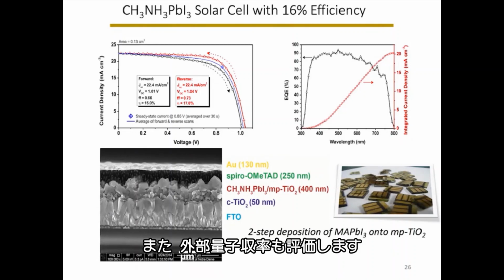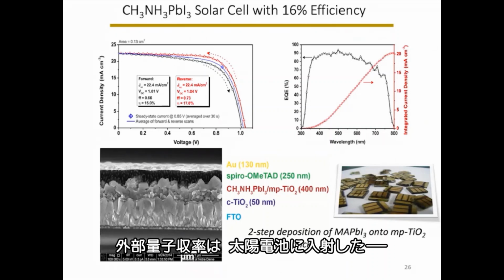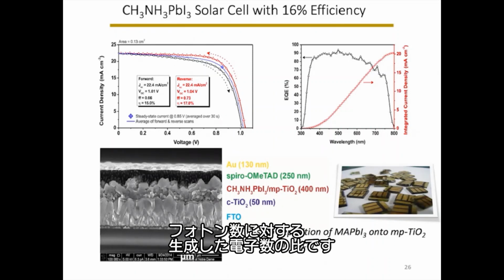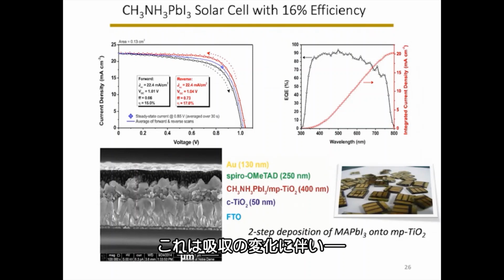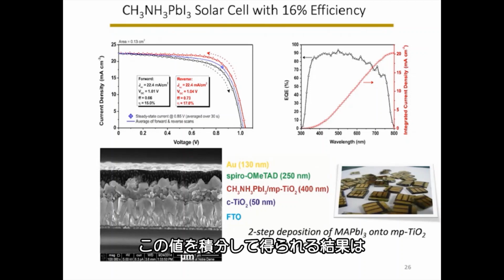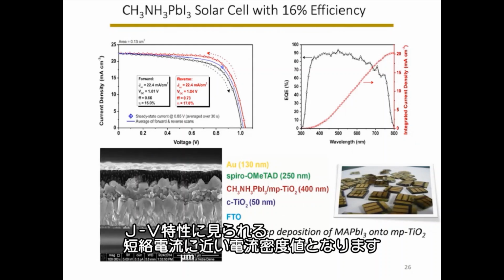Another thing we also evaluate is external quantum efficiency, which is again the number of electrons generated per number of photons incident on the solar cell, and it varies because of the absorption changes. It varies from 300 all the way to about 800 nanometers. You can see how the performance looks, and once you integrate this, you should get values of current density close to the short circuit current that you see in the JV characteristics.